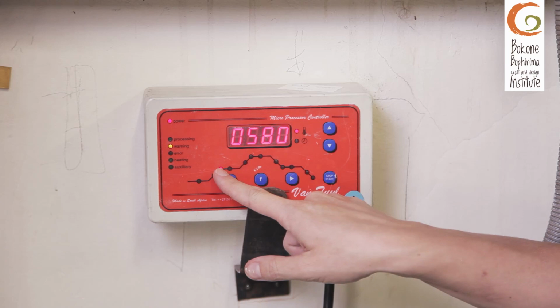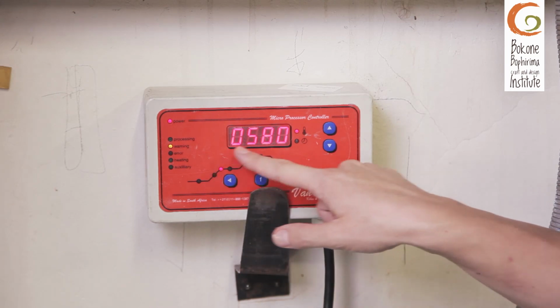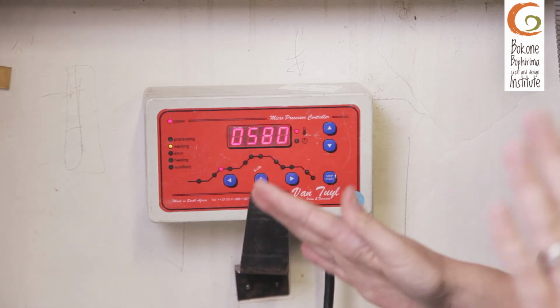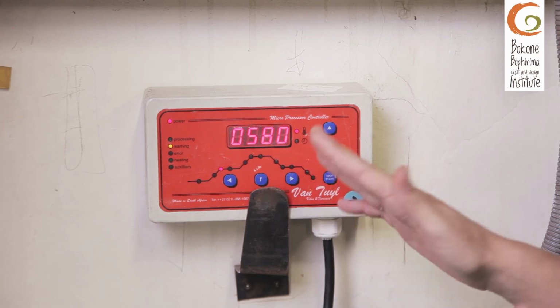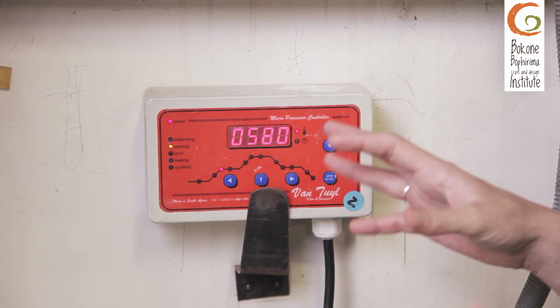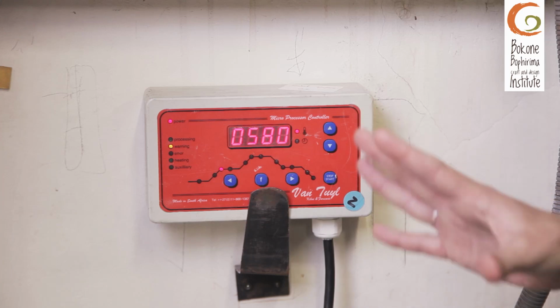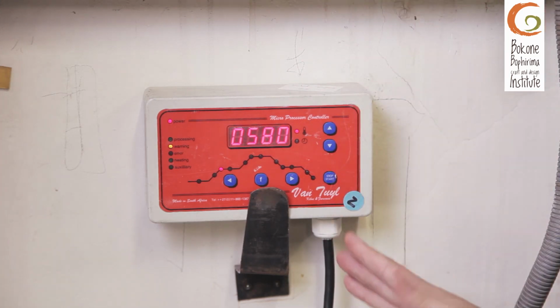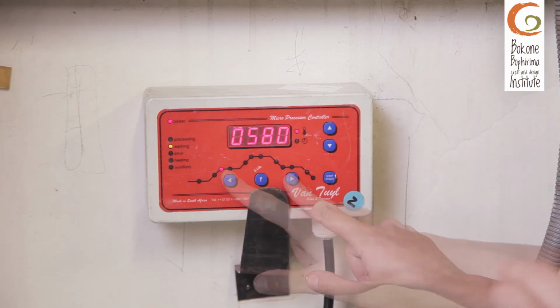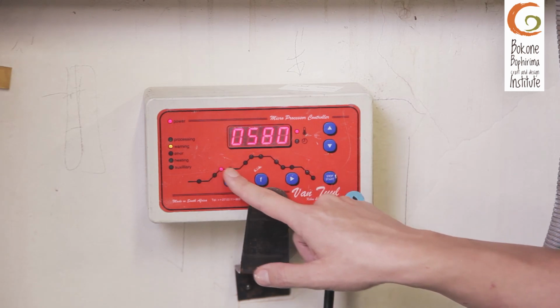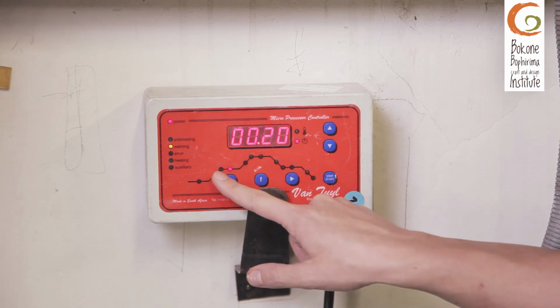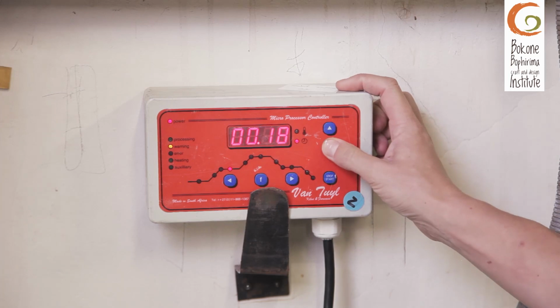Okay, our next section where we're going to allow our glass to soak is at 580. Anything between 60 and 580, our glass is under stress. So it's a point where we want our glass to go up slowly or go down slowly. So always keep that in mind. So now we're at our midpoint of 580, and I'm going to now put a soaking point of 10 minutes in.